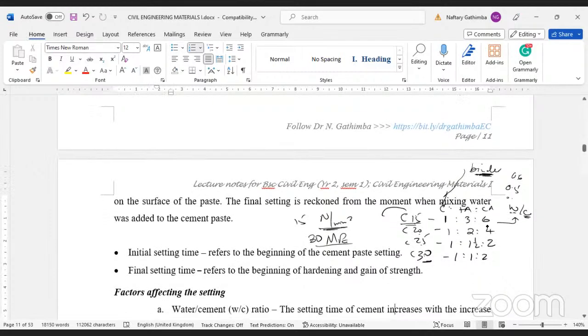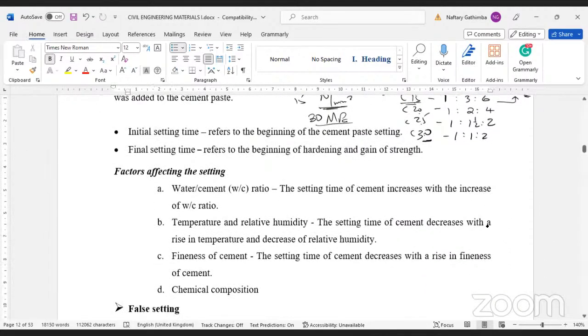Now, when you come here to the factors, we are mentioning the factors that affect the setting time. And one of them we said is the water cement ratio. So the higher the water cement ratio, if there is too much water, then it means the setting time will increase, okay? Again, if the temperature is high, if water evaporates quickly, then your cement paste will set fast. And also the chemical composition. The chemical composition will affect the rate at which the hydration process progresses.